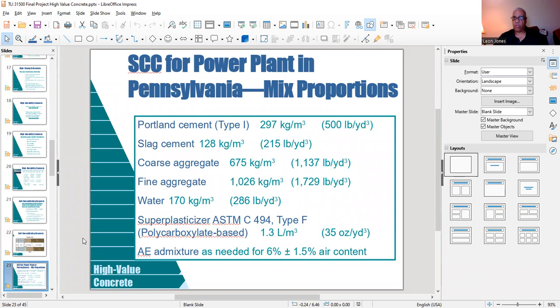All right, self-consolidating concrete for a power plant in Pennsylvania, mix proportions. This is good data right here. And if you're going to design concrete in the lab, in order to sell it, you need to come up with some good numbers. Well, for Portland cement, type 1, 500 pounds per cubic yard. For slag, 215 pounds per cubic yard. Here's your coarse aggregate, right around 1,140 pounds per cubic yard, and right around 1,730 pounds per cubic yard. That's your fine aggregate.